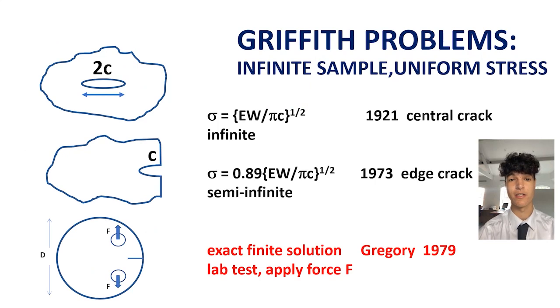The Griffith equation had three major problems. First, it assumed an infinite sample. Then, it had a central crack. Third, it assumed uniform tensile stress, which is difficult experimentally. Amazingly, it took more than 50 years to obtain the edge crack equation here. This requires 11% less force for fracture than Griffith's, so it's more dangerous.